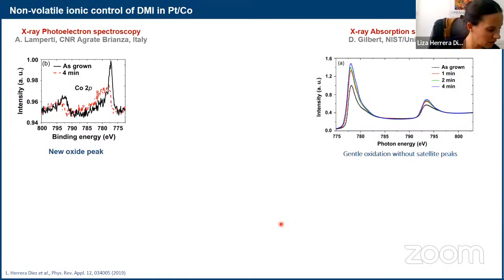So I showed you already the XPS evidence of the cobalt oxidation. So we also see the evidence in X-ray absorption spectroscopy. What is interesting from XAS is that we don't see satellite peaks for the cobalt oxidation. We just see an increase in the amplitude, which goes in line with oxidation, but it's not a brutal oxidation. We know very well the system has PMA, it's still very much magnetic, so it's a very, very gentle oxidation.